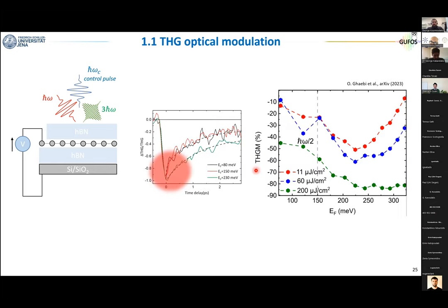There is one final thing now that we know that we can have this tunability. So now I told you that in graphene, we can control the third harmonic electrically and we can change the modulation. We can control the dynamics because we can make it slower or faster depending on the value of the Fermi energy. And we can also control the total amplitude in an all optical fashion. Because now you see that the third harmonic modulation, so if you take the maximum of these dynamics, here it's all normalized, but here you see it in percentage.